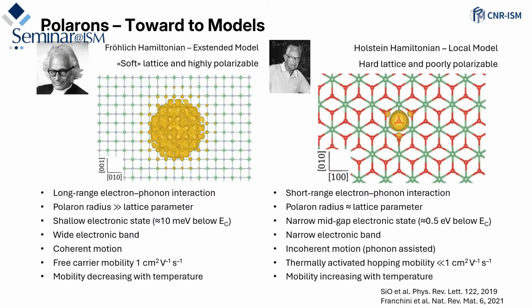Of course, these two theories bring totally different characteristics for the two kinds of polarons. So the first one is the extended model, the large polaron. What happens is that the interaction is long range, as I mentioned. The polaron radius is more than the lattice parameter of the unit cell, of course, so it's extended over many lattice units. We have a shallow electronic state, so we have trap states which are very close to the conduction band, and of course the major fact is that we have more coherent motion of carriers across the lattice, and this coherent motion is reduced when we increase the temperature. So the mobility of the system decreases with the temperature.